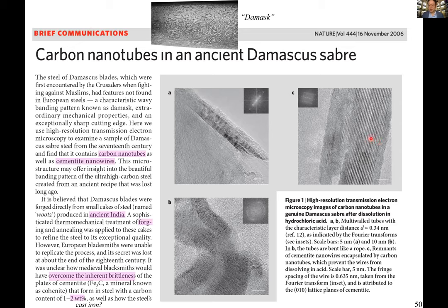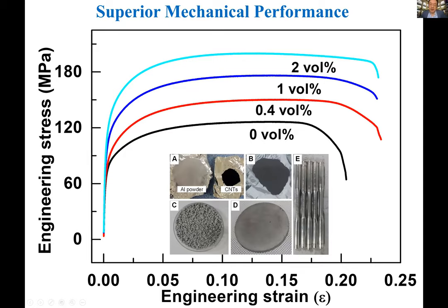So here you actually see a multi-wall carbon nanotube. The layer spacing here is matching that of the graphene spacing. And also this has a huge amount of carbon in it. Actually, this is up to 2.8% carbon. So you would say this is cast iron, this is not steel, but yet this is both very strong and very ductile. So what Kang Pyo has done is he was able to disperse this in aluminum up to 2 volume percent of carbon nanotube. And this is the tensile stress strain curve.